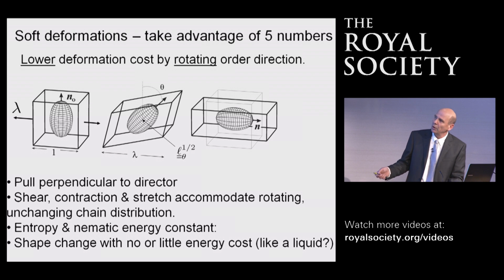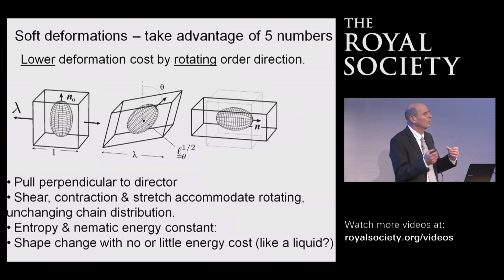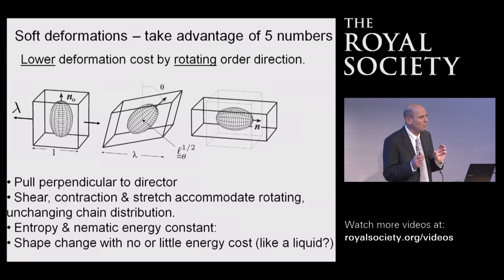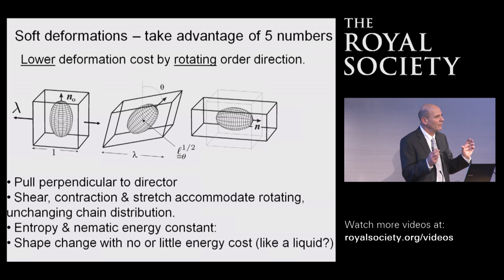Whereas if I'd pulled along here, or I'd pulled further along here, rotation doesn't help me, and it would have been stretched like an ordinary body. So it does both things, depending on quite how you attempt to deform it. And that is where we've deviated from Hooke. What we say is we have solids where some of the extensions don't cost energy and some do.